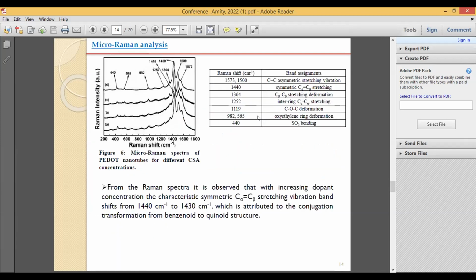And then we have done the micro-Raman analysis also. In the micro-Raman spectra, all characteristic vibration bands are observed, but one important point is that with increasing dopant concentration, the C alpha-C beta symmetric stretching vibration is found to shift towards the lower wave number region. This indicates a conjugation transformation from benzenoid to quinoid structure. We know that the quinoid structure is more well ordered, so we can correlate this with the XRD results and the micrographs.